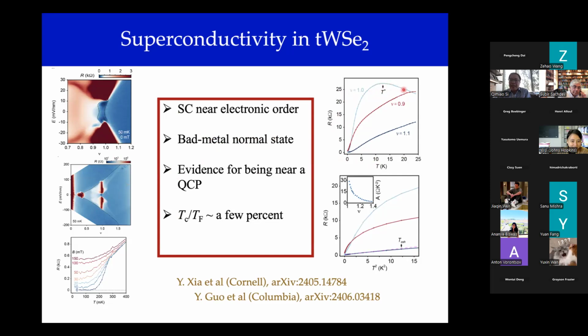And this kind of temperature dependence of resistivity is also interesting. It defines a scale that could be considered as, based on experience, we say something like a heavy correlated material like a heavy fermion. So if one can reach high enough temperature for the bad metals of Mott systems, presumably there are features like that as well. One could define that as a Fermi temperature. And in fact, by that measure, T_c, even though the absolute value is not all that large, the ratio is a few percent, and that's very much what one sees in heavy fermion superconductors and a variety of correlated superconductors. And finally, there's evidence for proximity to quantum criticality.